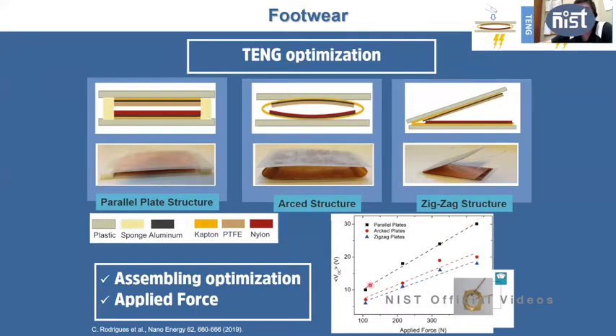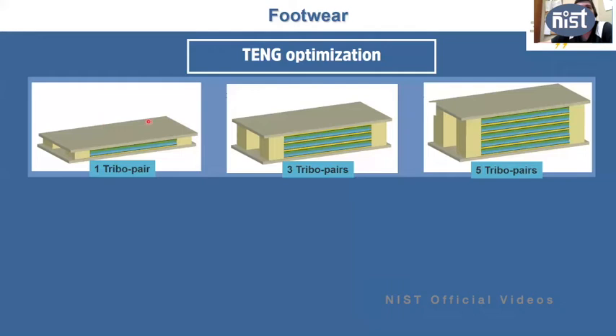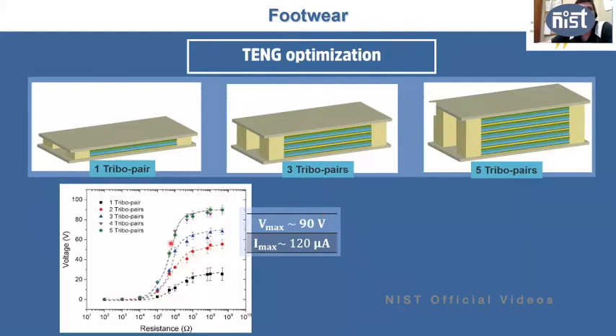We have changed the force, and they are linear with the force. This can be important if you want a sensor, and we will talk a little bit about this later. But the 3 of them are linear, and after this we focused on the parallel plates because it's the one that gives you the higher output power. You can also change the number of pairs that you put there. We went from 1 to 5. I'll show you some of the results.